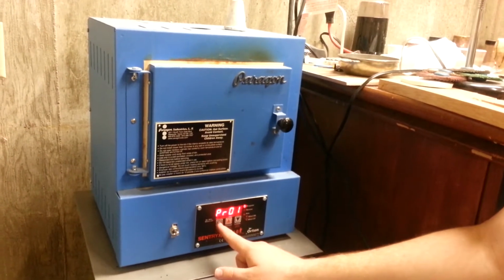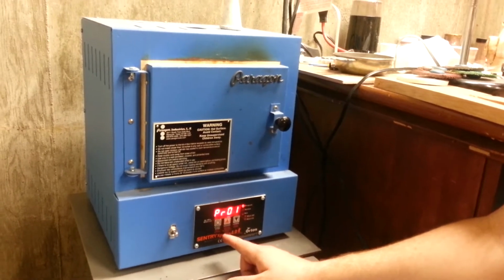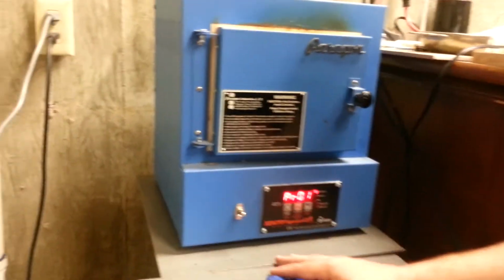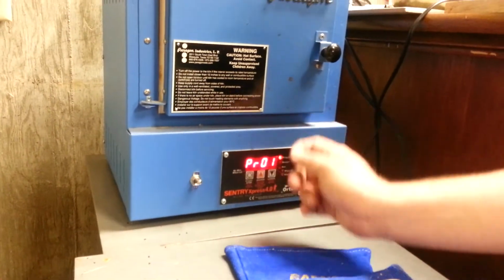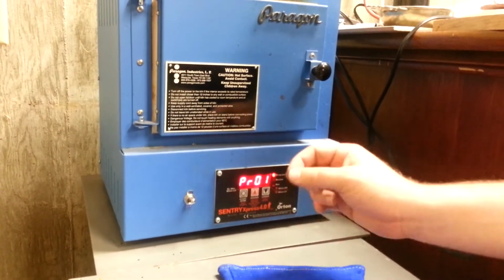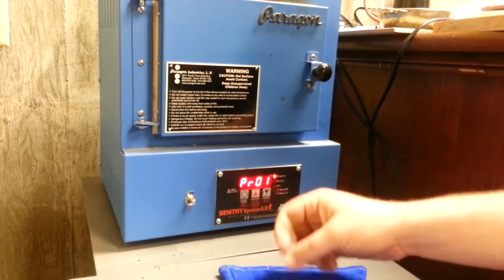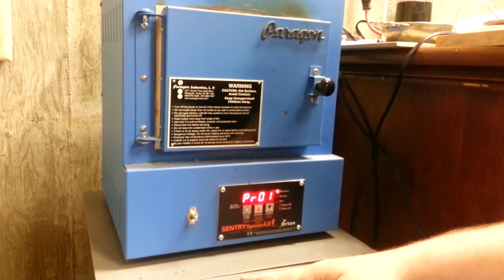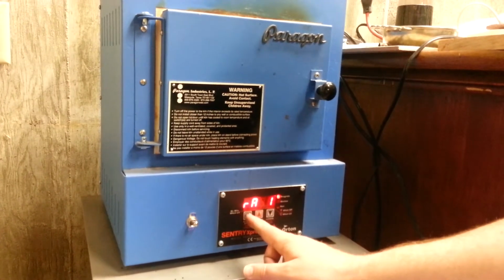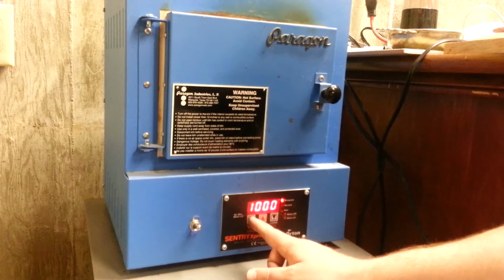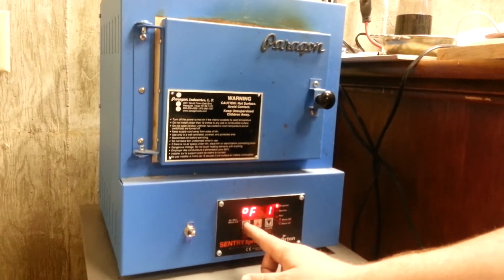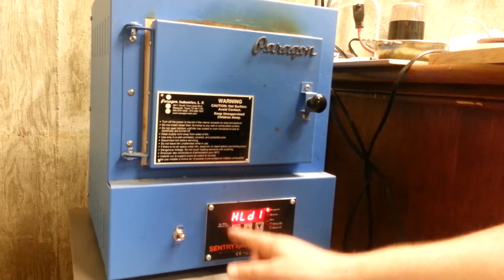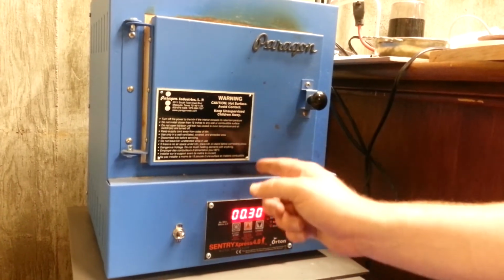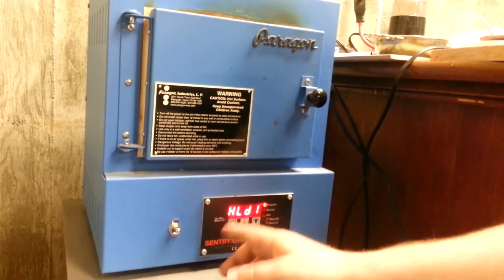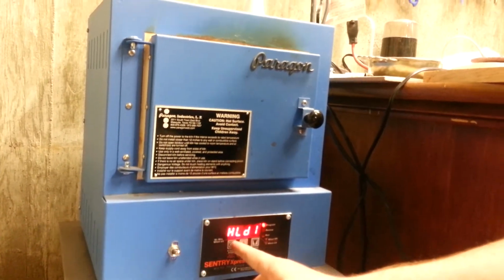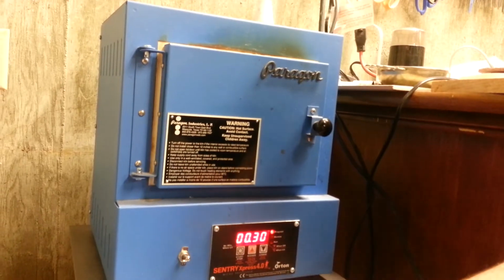And then I have this preset to do 2 different phases in firing. The first phase removes the methyl cellulose by burning it off, and then the piece will be black after that. The second phase you do in activated carbon, and that's what actually brings the pieces together and sinters them into effectively a piece of metal. So program it at a rate of 1,000 degrees per hour Fahrenheit, and then the last piece was going up to 1,000 degrees. So I don't want it to get any hotter than 1,000 degrees, and then I hold it there once it gets to 1,000 degrees for 30 minutes, and then it'll turn off and cool.